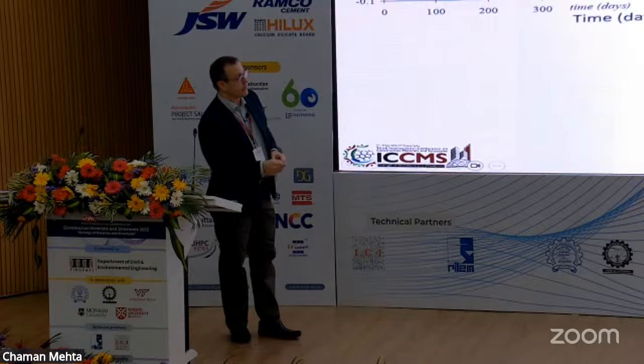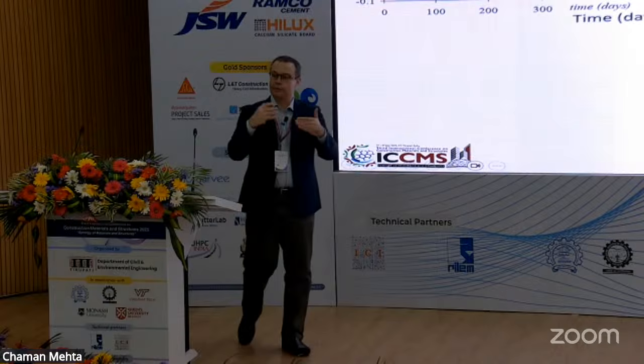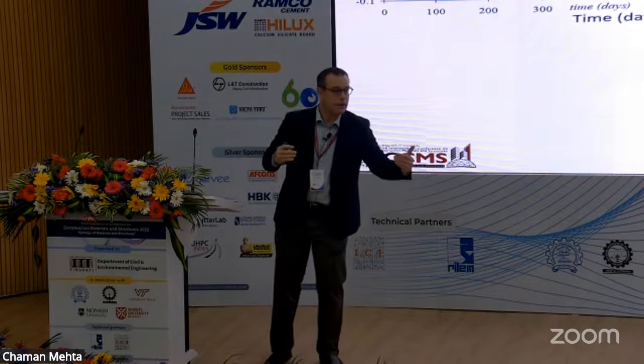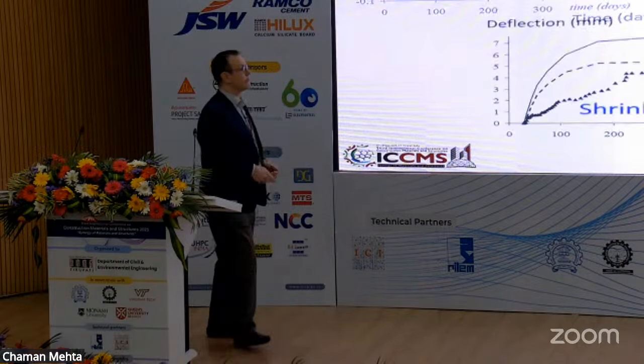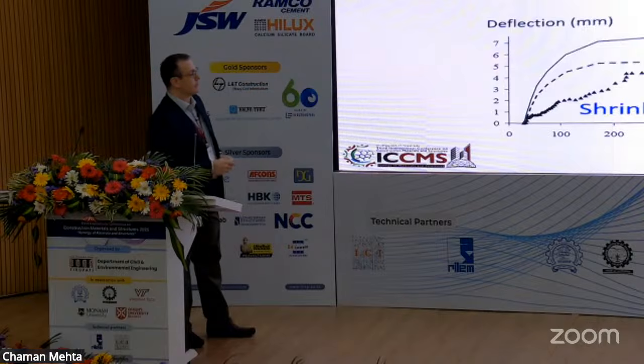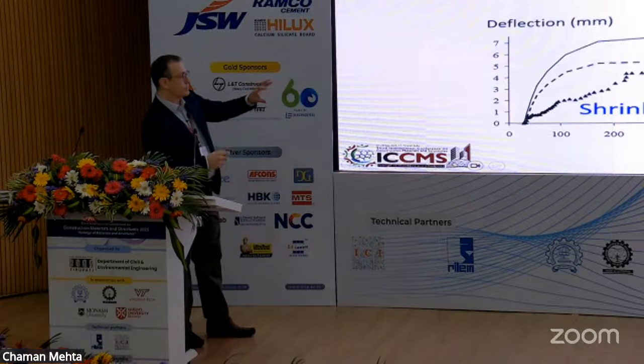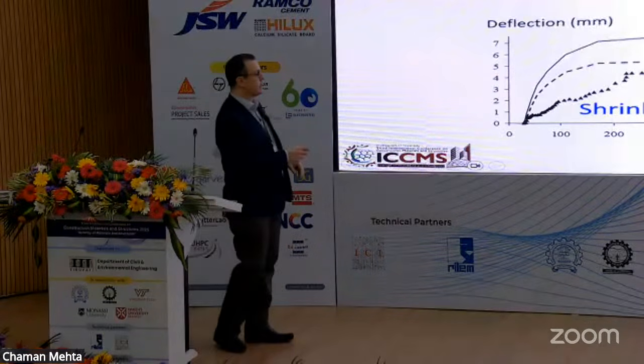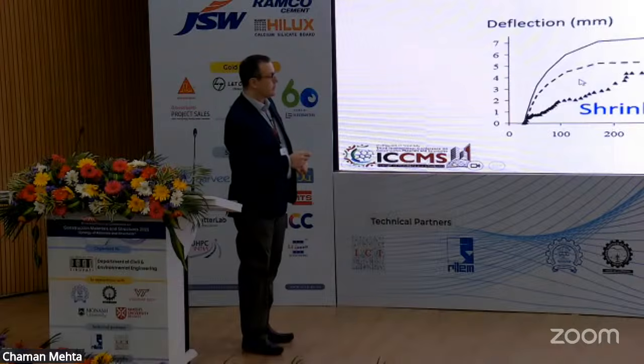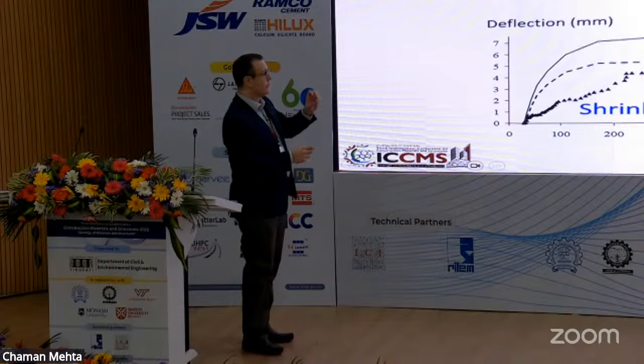So in this case, for example, the test rig that we did for a push-out test in the long term. I just want to show you that when you do advanced modeling, you have to push the experimental part as well, because otherwise it becomes a numerical exercise. And this is the interesting point, in the sense that these results are already post-processed. So in this case, you've got the 3 beams we saw before. In this beam, we got only the shrinkage effect. In these 2 cases, we got only the creep effect. So it's been already manipulated.